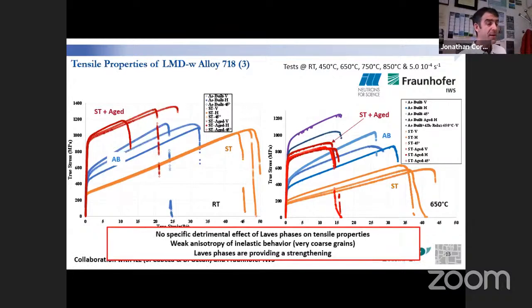So from those experiments, we saw no specific detrimental effect of Laves phases on tensile properties. We have overall a very weak anisotropy in inelastic behavior. I'm not speaking about the elastic part, in which we have anisotropy, as expected from the very large grain size. And we can see that Laves phases are providing a strengthening.